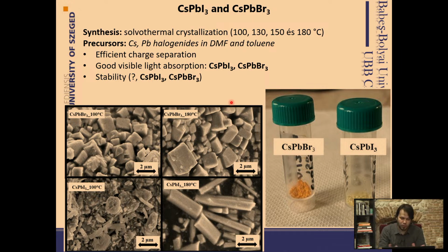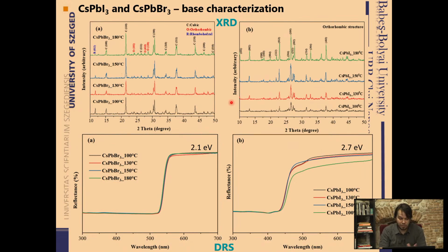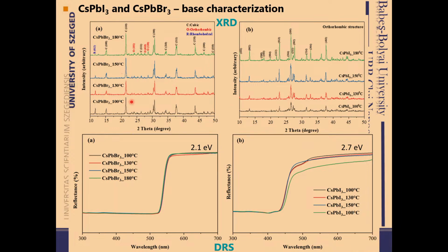So we have the nanoparticles, and we wanted to analyze first if they are what we think they are. So we have taken some other measurements. I won't bore you with excessive details. The most important thing is we did X-ray diffraction. The takeaway note is that all the reflections which you see here are in the same place, which means that the material which we have obtained is indeed cesium lead bromide, or in the other case, cesium lead iodide. So this was the purpose of the first investigation. The second one was an optical analysis, to find out if their color is appropriate for visible light absorption. And indeed, for the cesium lead bromide and the iodide, these values for the excitability of these materials were perfect. Other details are not important regarding today's presentation.